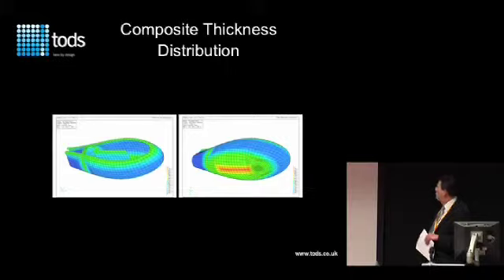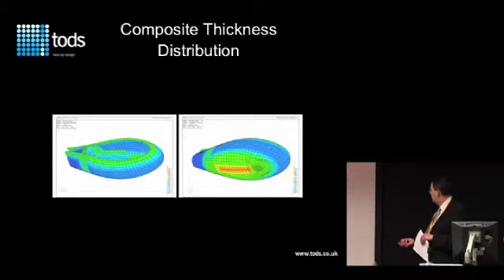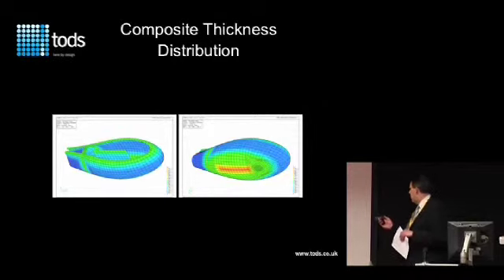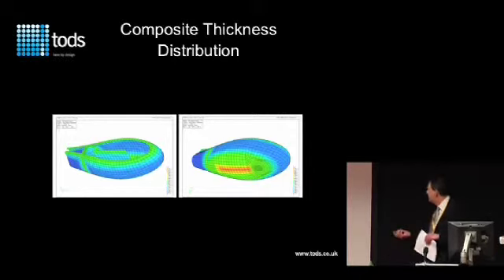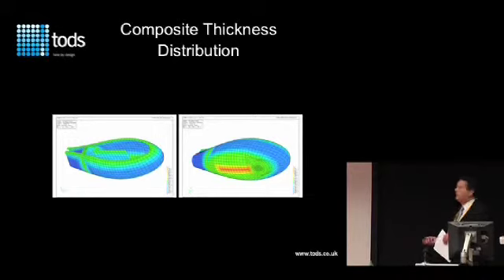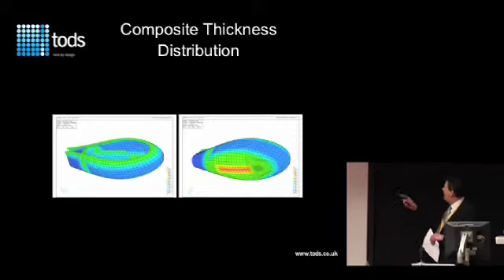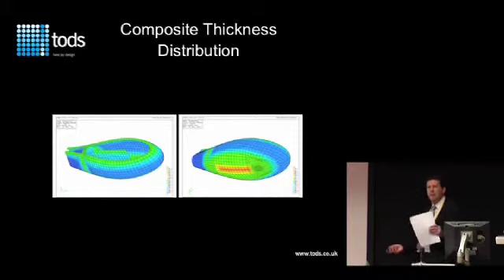This dome is the blue area. The blue area is the acoustic window. That's 25 millimeters thick. The red area on the base is 100 millimeters thick, and the flange area is 75 millimeters thick. So it's quite a big structure.